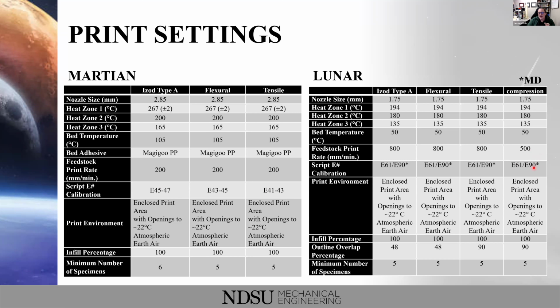And we believe that led to a couple of minute differences in mechanical properties in the end. But other than that, the print settings were very similar across the board for both of them. Obviously, different temperatures for the different materials, that type of thing. Our polypropylene, we did get to stick to our bed using the Magigoo PP. Basically, it's a glue stick for additive manufacturing.